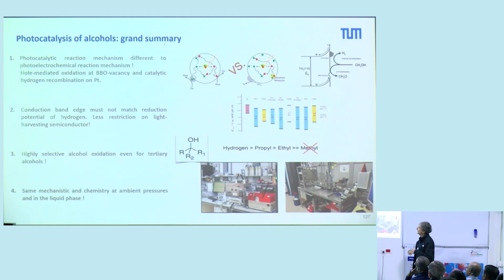So this is a summary of this part. I showed you that the photoreaction mechanism is different from the photoelectrochemical pictures. We have a hole-mediated oxidation at BBO sites and a catalytic hydrogen recombination at the platinum sites. I hope I could show you that the conduction band is thus not important because we don't have a reduction. And I also showed you that we can even oxidize tertiary alcohols in a very selective way.